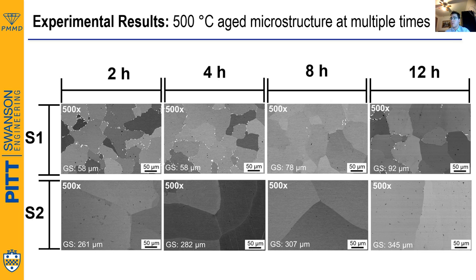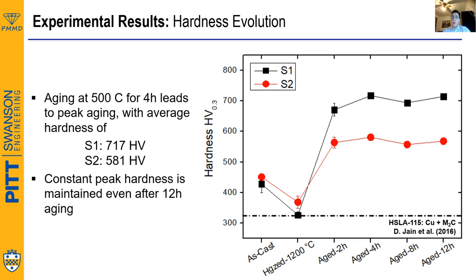But for the case of S2, a constant increase in grain size is observed as aging time is prolonged. Now, in order to quantify the mechanical properties of both S1 and S2 at their multiple heat-treated conditions, we use Vickers hardness testing. We set the parameters to be 300 gram force with 10 seconds dwell time, and the data points that you see here in the figure correspond to an average of 10 indents. While the as-cast and homogenized hardness of both samples is basically the same, the hardness of S1 clearly outmatches S2. Peak aging hardness for both samples is reached after 4 hours of aging, and S1 reaches a record high hardness of 717 HV, while S2 reaches a value of 581 HV.